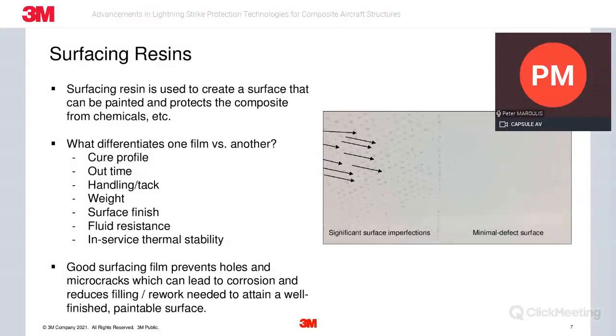The cure profile is also key. Some films are only 250 Fahrenheit or 121 Celsius cure. Some are only 350 Fahrenheit, 177 Celsius cure, and a few, and more recently, some additional ones are dual cure at both of those temperatures. Keeping weight out of the structure is always a top priority. We've touched on the chemical resistance just before with the paint stripping process. And the in-service thermal stability due to thermal cycling seen on the exterior surface of the aircraft is also important. Next slide.